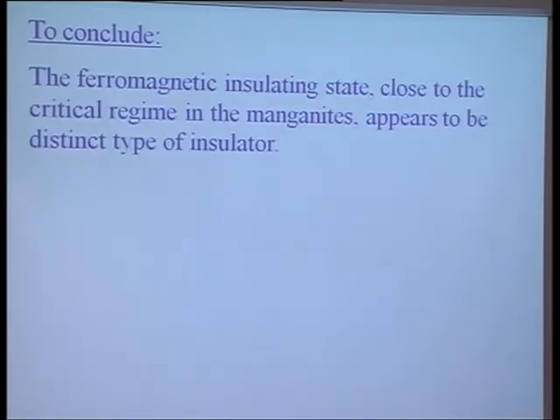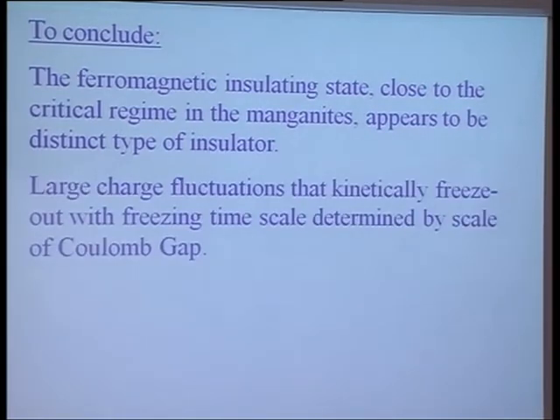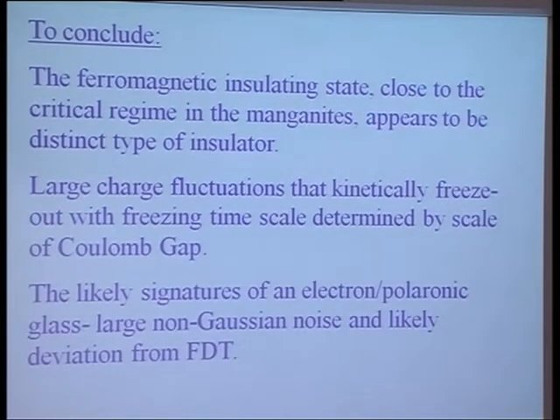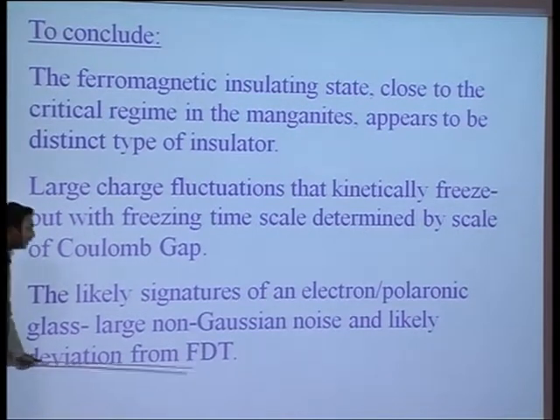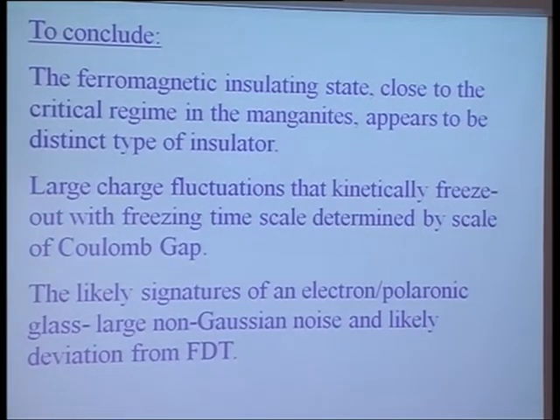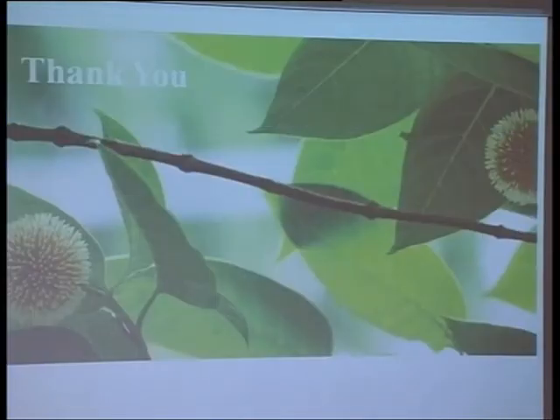So let me just conclude my talk. What I gave you is that if I take the ferromagnetic insulating state close to the critical region, there appears to be a distinct type of insulator. And in this region, we see large charge fluctuation that can kinetically freeze out. And the time scale for the freezing out is essentially determined by the Coulomb gap. And we also find likely signatures of an electronic glass, which has a large non-Gaussian noise and likely deviation from the fluctuation dissipation theorem. The last one is something we are currently working on, and we are now getting reproducible data, but the analysis is where we have got stuck. So I'd like to thank you.